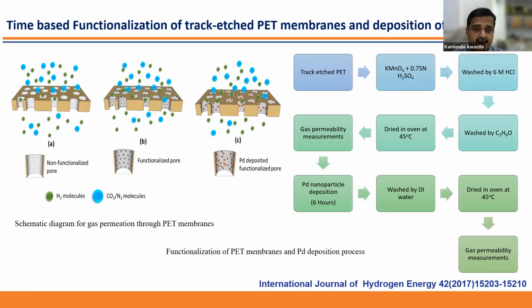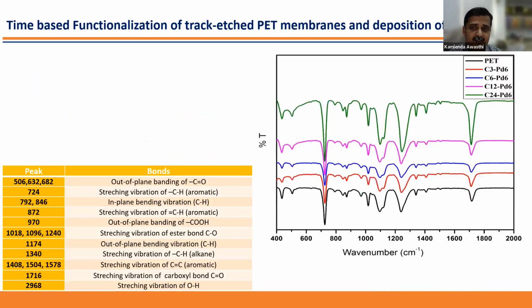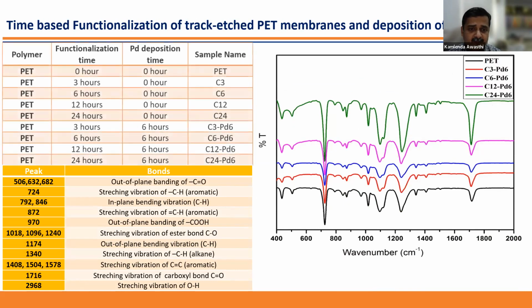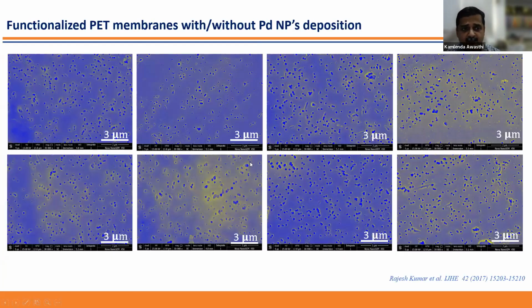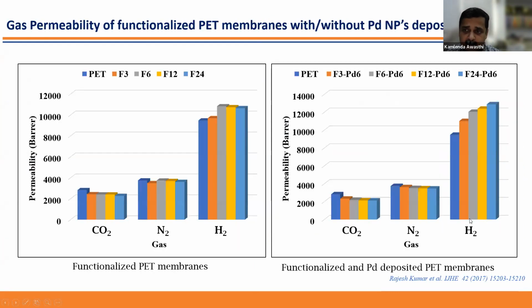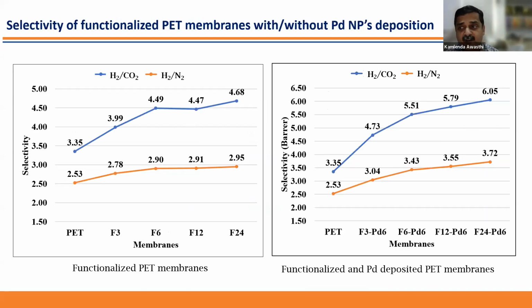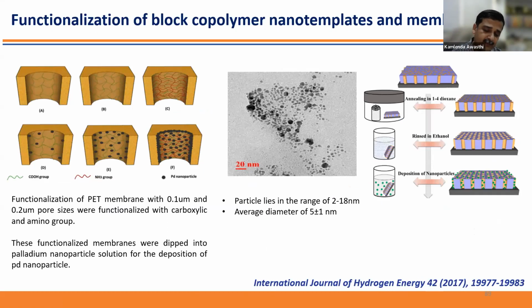So earlier we did the random functionalization, so we tried to increase it. We tried for different times up to 6 hours, and you can see here this is for different timing. As we increase the time, this brightness means you can see more palladium nanoparticles depositing over the surface. So it means the attachment of this palladium nanoparticle in this functionalized membrane helps us to control the selectivity of the gases. Here you can see, earlier in the pristine membrane, the selectivity, meaning the ability to pass a particular gas, was around 2.53, and that we can raise up to 3.72, and here from 3.3 to 6.05. So certainly it helps in track-etched membranes.